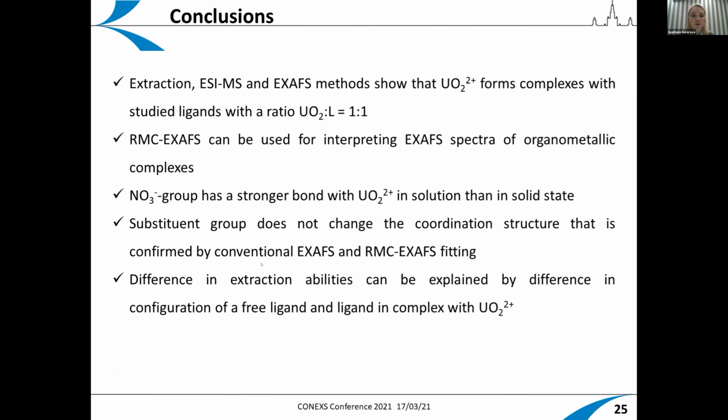Nitrate group has a stronger bond with uranyl cation in solution compared to solid state. And substituent group does not change the coordination structure. That is confirmed by fitting both by conventional EXAFS and the reverse Monte Carlo methods. And difference in extraction abilities can be explained by difference in configuration of a free ligand and the ligand in a complex with uranyl cation.